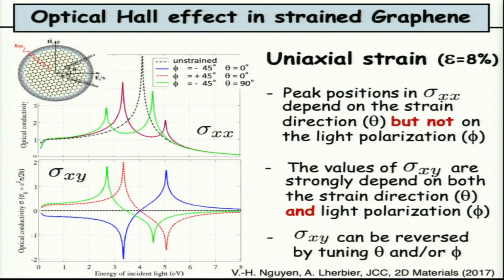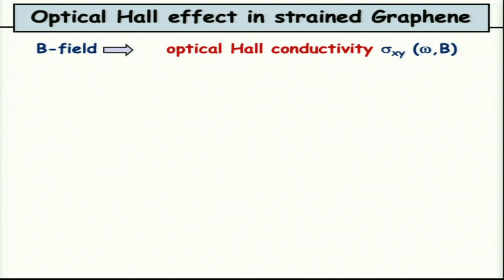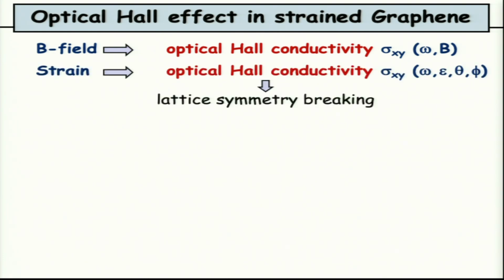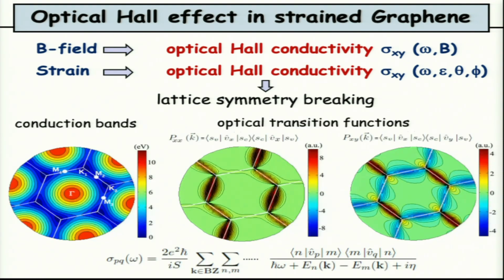Okay, so sigma xy, so the optical Hall conductivity, can be reversed just by tuning theta and also phi, so the polarization of the light. So, as I mentioned, a magnetic field can lead to optical Hall conductivity, but the strain as well. And this optical conductivity is much more rich because, in fact, it depends on 4 different parameters. So, the energy of the incident light, the direction of the polarization, the direction of the strain, and its amplitude. So it's quite a rich model which is induced by this lattice symmetry breaking.